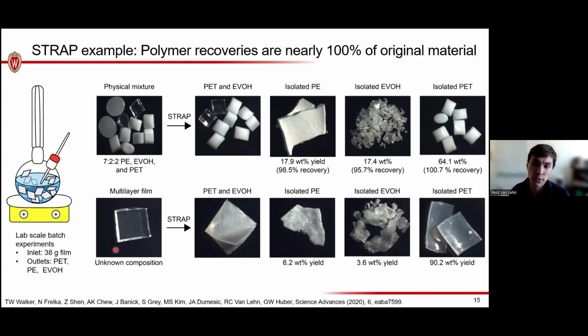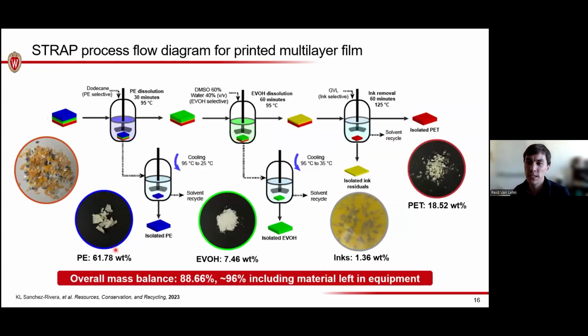Okay, I am a chemical engineer, which means we show lots of what are called process flow diagrams with arrows pointing to where different things go and different temperatures. This is now the process flow diagram for that slightly more complex material that has the ink in it. And we can see that as we choose different solvents, we heat them up, we cool them down, we can extract polyethylene, EVOH, we can pull off all that orange ink that was in the label, and then finally we get our isolated polyethylene terephthalate. Now, this ink is an example we'll call a contaminant, and I'll come back to that in just a minute.